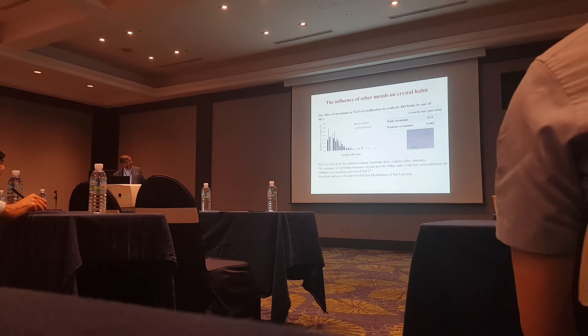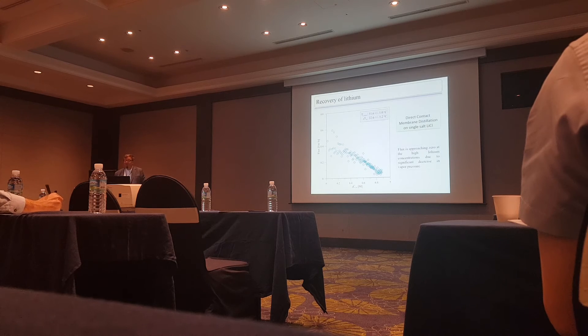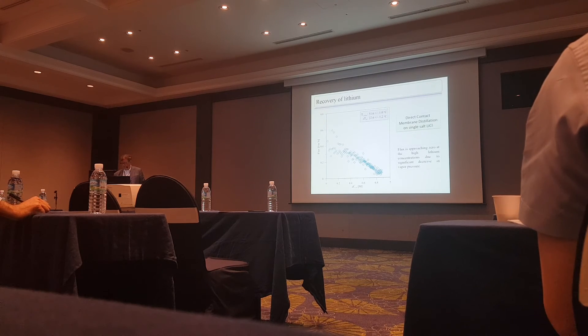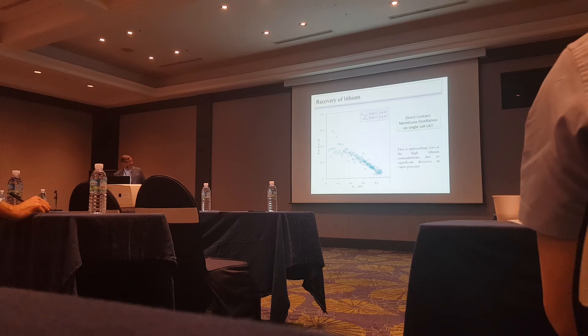However, it is not so easy. To show you one case: if you want to extract lithium from the sea, you will not have any success with traditional direct-contact membrane distillation. At 50°C, lithium requires a supersaturated solution at 14 molar to crystallize. You will never reach that concentration using direct-contact membrane distillation — you go to zero flux at around 9–10 molar, well below the crystallization point.